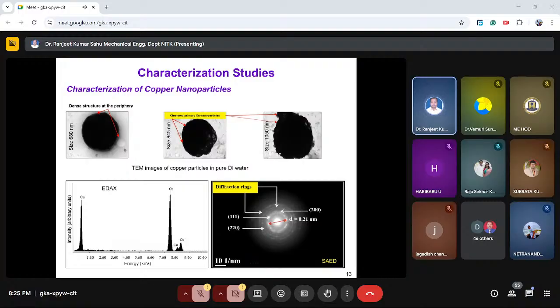That is, after 4 hours of the collection, the particles have settled down. So to overcome this problem, what happened? As per the surface chemistry of the copper particles and DI water, some polymeric stabilizers are adopted in this study. One stabilizer we have used is polyvinyl alcohol, PVA, which can study the effect of interaction between the nucleated particles as per the surface chemistry.